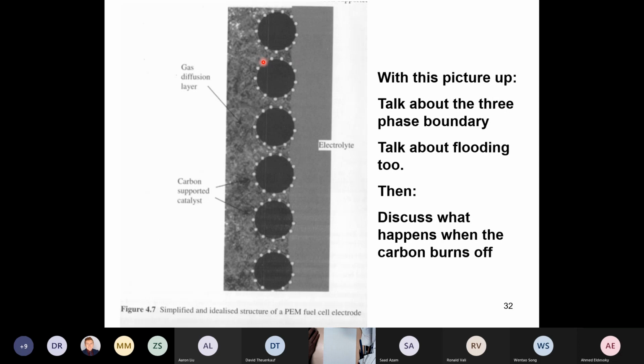Look at these catalyst particles back here. Is there any way a proton can get to them? There is no way a proton can get to these catalyst particles back here. So these catalyst particles back here are wasted. All that platinum, which costs a ton of money, is doing nothing, because the protons can't get to these guys. So it's important when you put the catalyst layer onto the gas diffusion layer that you also include Nafion ionomer, which is kind of like a binder, so that you have a proton path to the majority of the catalyst particles on the carbon black. Otherwise, the platinum's wasted.